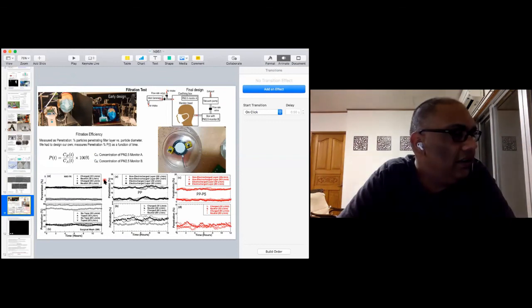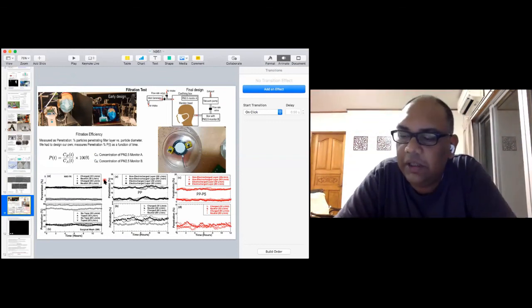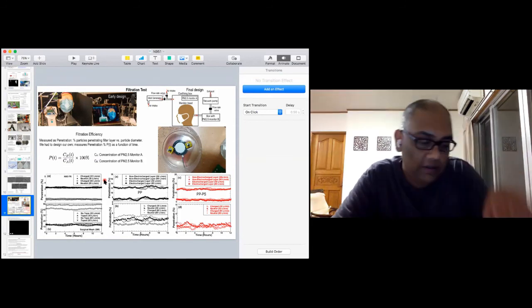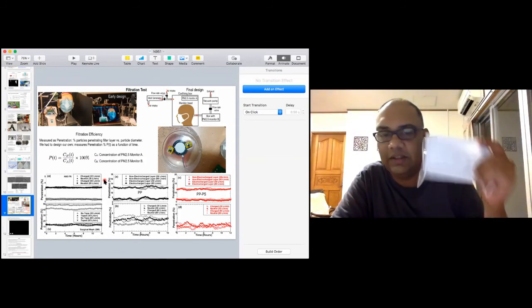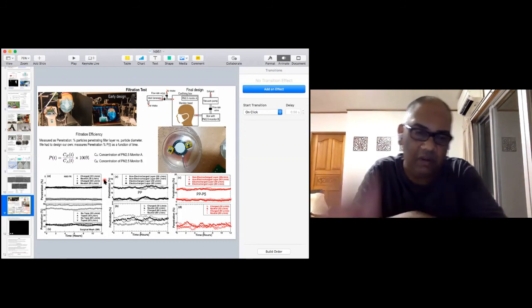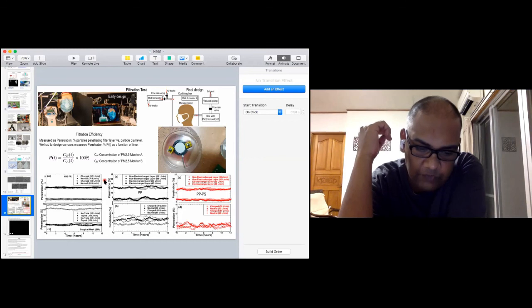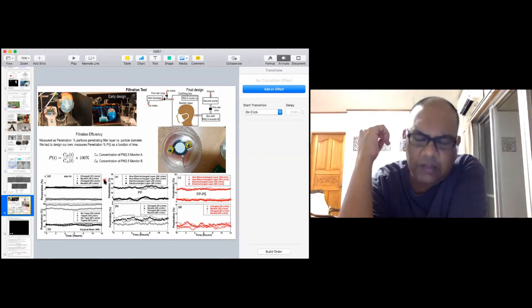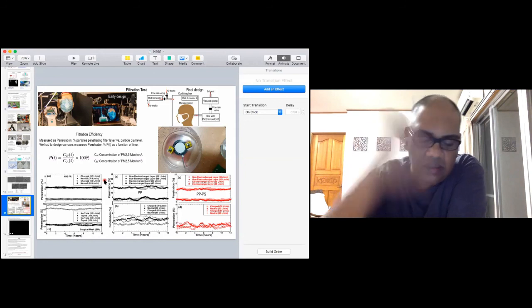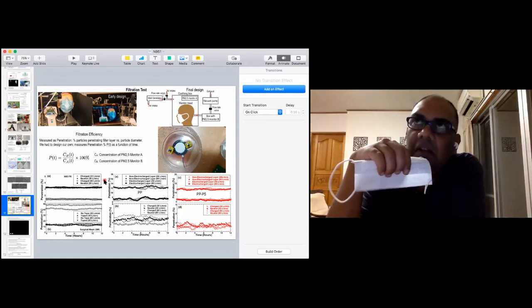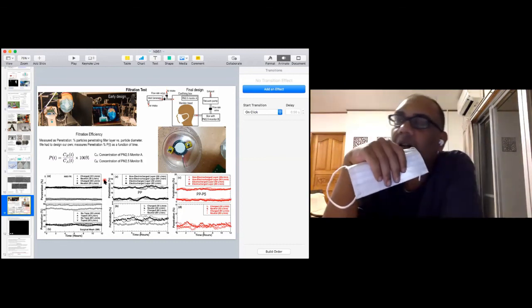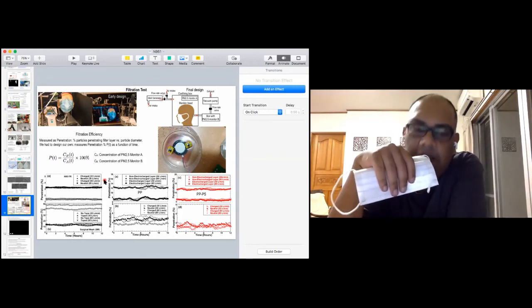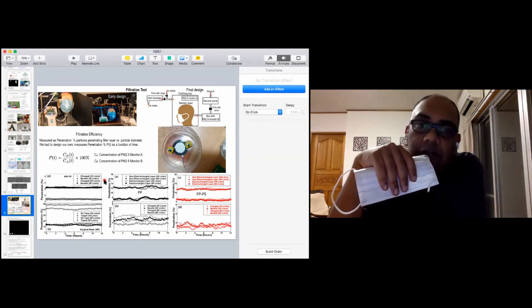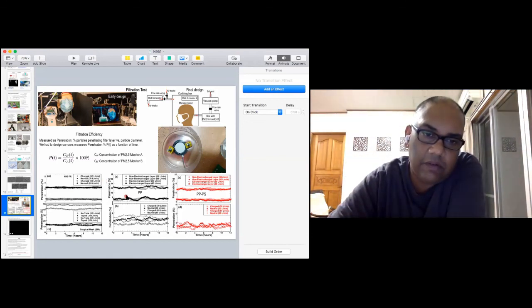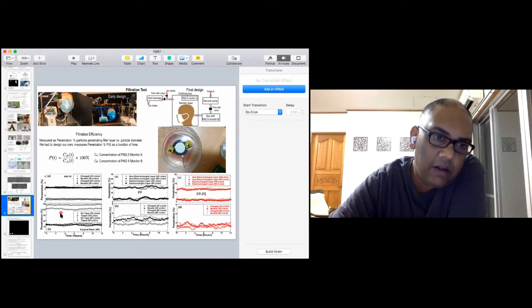So I don't have the data with me, but that has been published actually. There are two papers which did this, not with homemade cloth masks, but with surgical masks, and the distribution ranged from about 30 to 50 nanometers up to a micron or so. And these masks were not doing so well. Basically, the filtration got worse as the particle size fell, and it was of the order of 40 to 50%. So it's not far off from the result I got for this plot over here.